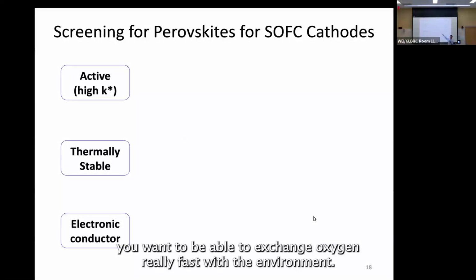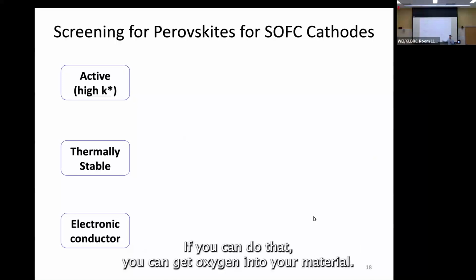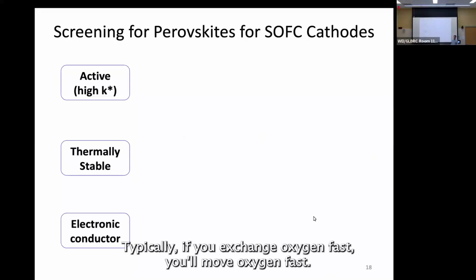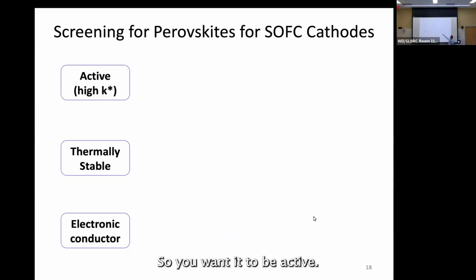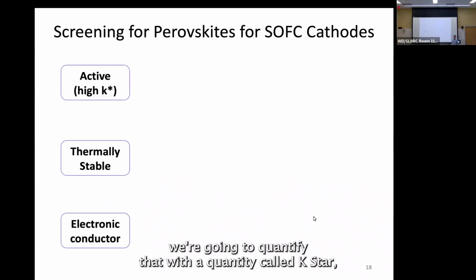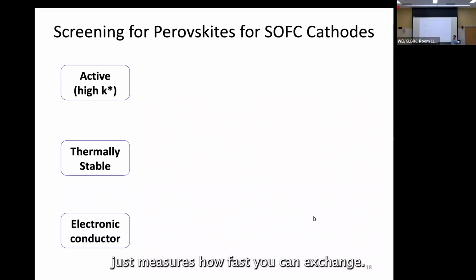be able to exchange oxygen really fast with the environment. If you can do that, you can get oxygen into your material. Typically, if you exchange oxygen fast, you'll move oxygen fast. So you want it to be active with respect to oxygen. We're going to quantify that with a quantity called K star, which is called the surface exchange coefficient. It just measures how fast you can exchange oxygen with the surface.